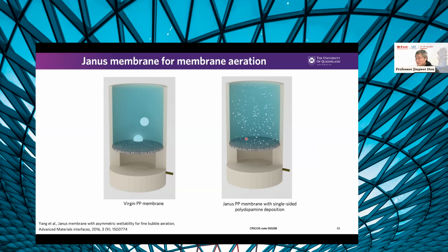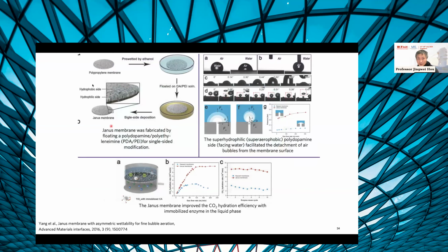Okay, so what happens if we use a Janus membrane? We can achieve fine bubbles. So this is what we did. We have polymeric membranes made from polypropylene, very cheap, commercially available. Then we coat the membrane on one side with a hydrophilic coating. So we now have a Janus membrane. One side is hydrophilic, the other side is hydrophobic.